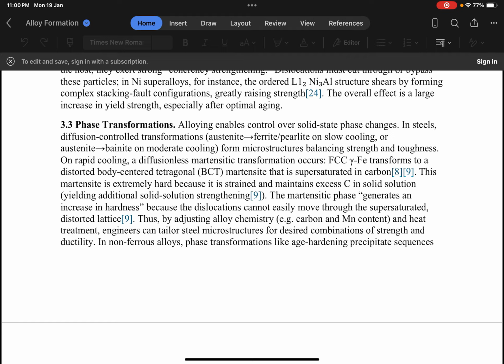Face centered cubic gamma iron transforms to a distorted body centered tetragonal, BCT, martensite that is supersaturated in carbon. This martensite is extremely hard because it is strained and maintains excess carbon in solid solution, yielding additional solid solution strengthening. The martensitic phase generates an increase in hardness because the dislocations cannot easily move through the supersaturated distorted lattice.